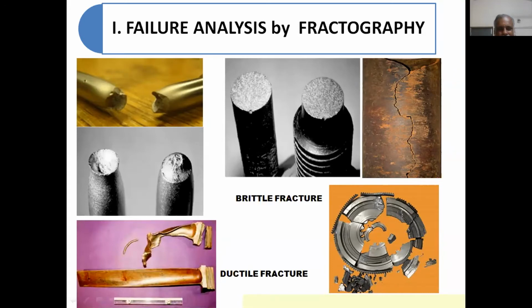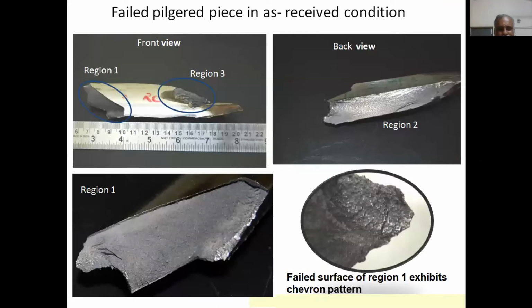Let me go into the case study where you have been given some samples. This was basically an extrusion. You see on the left side, region 1, region 2 I have marked, and this was cold extruded, or pilgered rather. When it was driven through a die, it came out in pieces like a crocodile mouth. If you look very carefully with the naked eye itself, you could see some signatures. On the right corner down here, these lines are there. Good fractography people will understand that this is basically a brittle failure. The shininess on the surface plus the lines suggest it is a chevron or V type of pattern, which means it has failed by brittle nature.